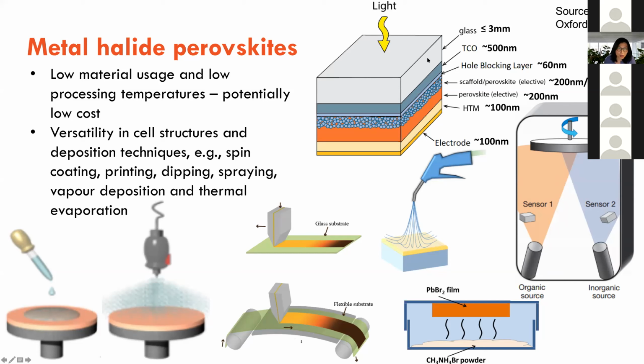So this is a typical cell structure. It's deposited onto what we call a superstrate, because in this case, the substrate, or the thing that the solar cell is deposited on, is also facing light. So it's called superstrate. It doesn't have to be glass. It could be plastic. It could be flexible glass. Then you usually have a transparent conductive oxide. Could be ITO, indium tin oxide, or fluorine doped tin oxide, FTO.